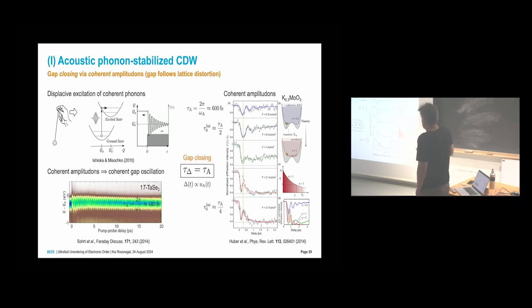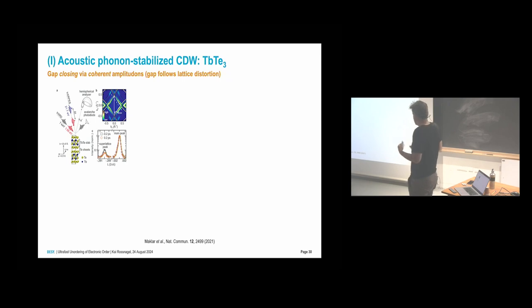Yeah? And here in this scenario, this vibration of your atoms is directly linked to the vibration of the gap. As you can see in time-resolved ARPES, you see these oscillations here. So here you have clearly a gap closing, coherent closing due to the vibration of the atoms, and the charge density and electronic structure changes are intimately tied to your lattice motion, to the amplitude of your lattice. This correlation has very nicely been studied by Martin Wolf and Laurenz Rettig in this study on terbium tritelluride, another important charge density wave reference material, where they have combined ARPES and X-ray diffraction.